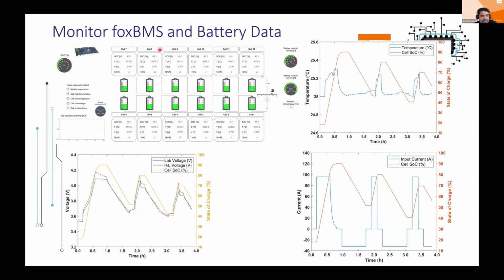After this, we also checked whether the Fox BMS balancing strategy is working or not. So we triggered the cell balancing, and once we triggered it, we found that every cell voltage and SOC was increasing rapidly, and the imbalance was around 2 millivolts, but in this case it is set up around 80 millivolts. So to initiate the balancing, we chose cell 4. Any cell we can choose, but for example we chose cell 4, and then found that it went to the balancing mode, and the balancing current, which is not showing here because this graphic was not updated, was flowing around 100 milliamperes during the discharging. And this was about the graphical user interface for the real-time monitoring of the BMS data.